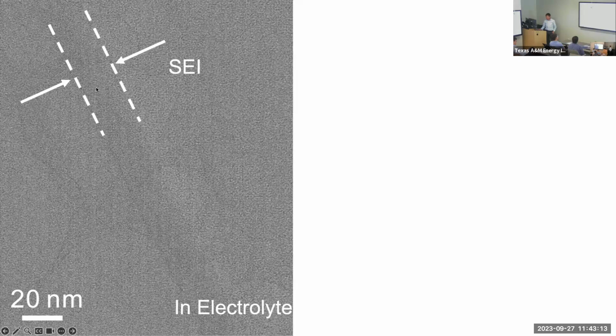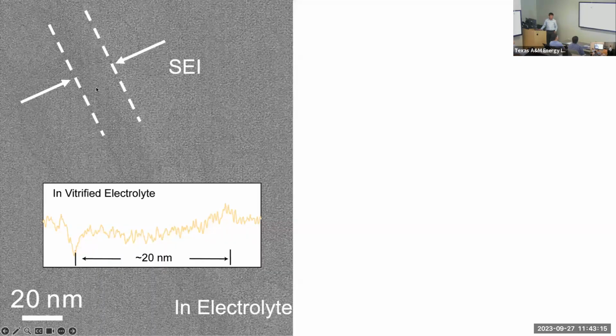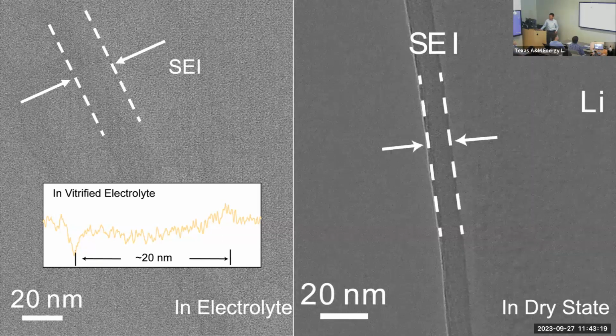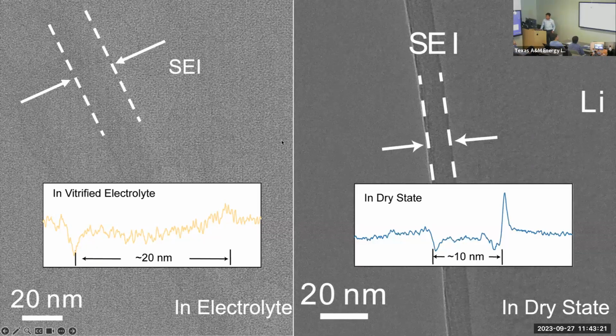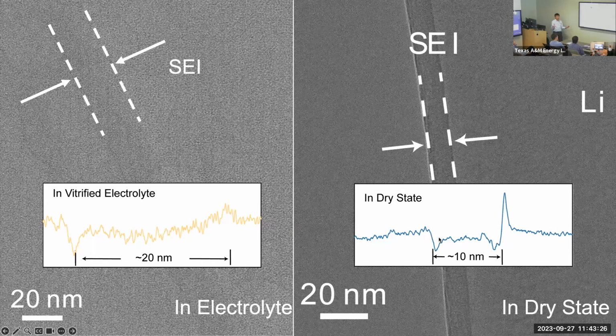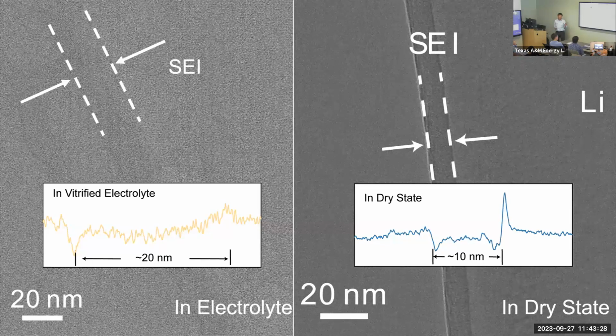This is the SEI layer, 20 nanometers for this particular electrolyte. We could also dry up this electrolyte, and then you look at the SEI again. This is only 10 nanometers, same electrolyte on the lithium. This is telling you this interface is swollen with organic liquid electrolyte under operation. The dry state is only half of the thickness.